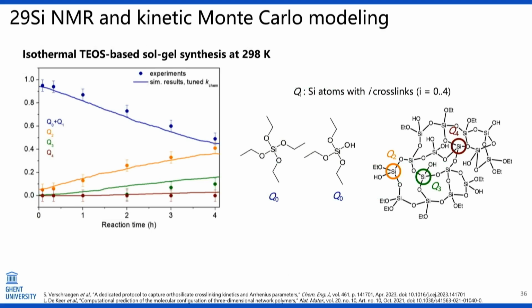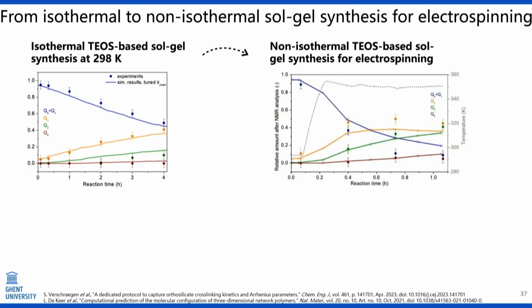So this is illustrating here that we've got a very good agreement of our model with our experimental data, and we can follow the QI species over time, both for isothermal synthesis and non-isothermal synthesis, which is needed for electrospinning.